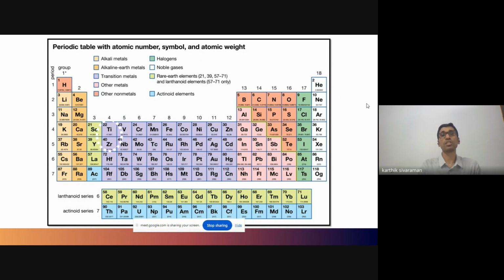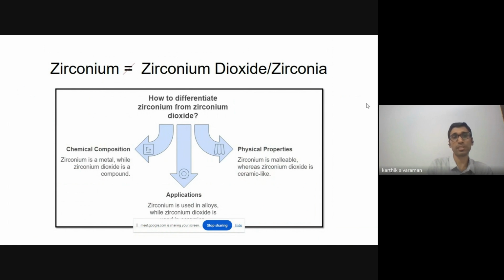On the other hand, zirconium implants are basically fabricated of zirconium dioxide. It's a combination of zirconium with oxygen, so we will be seeing an ionic bond and properties which do not conform with those of an alloy. What we need to reinforce is that zirconium metal is not the same as zirconium dioxide, also commonly known as zirconia. Zirconium dioxide, a ceramic oxide, is not similar to a metallic alloy. For instance, titanium and zirconium can be combined to form a solid solution, which is a metal alloy, but zirconium dioxide is not a metallic alloy. So the applications and the physical properties will vary.